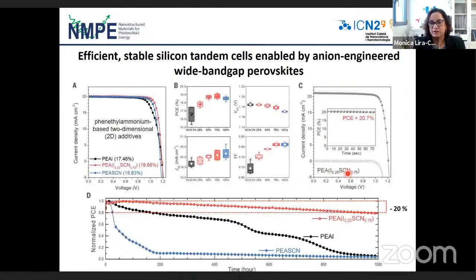So this is another example, a very recent one, from last year, and very nice work on tandem solar cells. In this work, they use different additives, two-dimensional additives, and you can see that the efficiency, depending on the concentration of the additive, increases when you optimize the amount used. For us it's very good because you increase the power conversion efficiency. However, when you look at the stability of the device, even though it lasted 1,000 hours, it lost 20% of the initial efficiency. So this is a very stable solar cell, but not stable enough to say our technology is already stable.